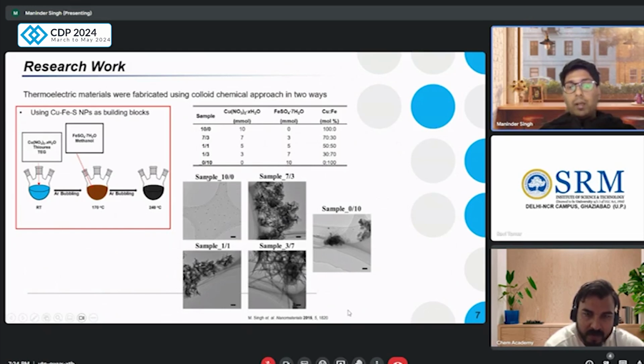So I created 5 samples, which are composed of pure copper sulfide particles and mixtures of copper and iron sulfide nanoparticles. So you can see the images, a spike formation. These are kind of nano flowers you can see. Nanoparticles cannot always be spheres; they can be of any shape, and they have shape-dependent properties. So we have to keep in mind that with a changing shape of the nanoparticle, the end property will change.